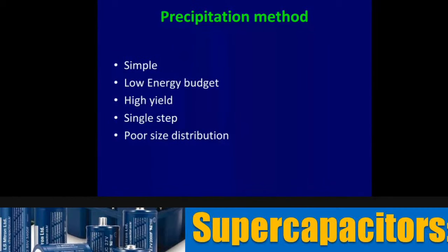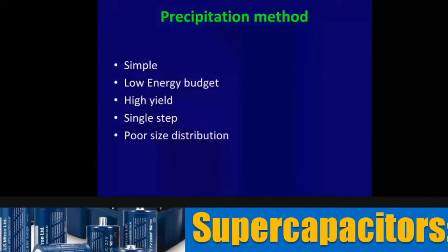So when you look at the precipitation method, all of you know that it is the most simple, elegant method. There is no energy budget. Most of the precipitation reactions take place at room temperature, and if you look at the yield, it is very good. You can get even 60-70% yield in the precipitation method, and it is mostly a single-step method.